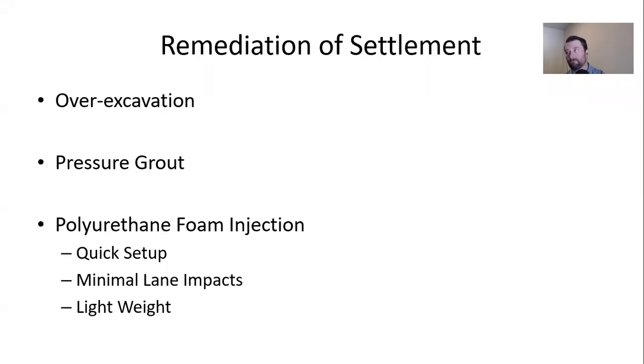Yeah. So, the speed at which you can do it, I think you inject it and it's pretty well set up within the next 15 to 30 minutes? Yeah, within 15 to 20 minutes. In most cases, we're at 90 to 100% full cure strength. There's variation to that, of course, depending on the circumstance, but that's pretty typical.